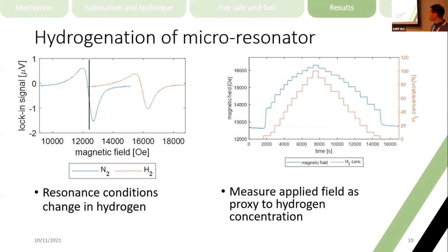How do we sense hydrogen with that? As I said, when the cobalt palladium absorbs hydrogen, the resonance condition changes. So I'll show here on the left-hand side a nitrogen and a hydrogen trace, and we see that they occur at different fields. And this is concentration dependent, so if we don't measure in pure hydrogen, the resonance would occur somewhere in between those two curves.